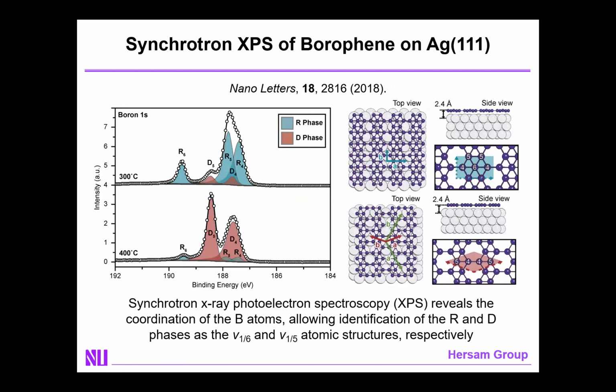And as a result, you need to use other methods, and one that was particularly useful was synchrotron X-ray photoelectron spectroscopy. And this allows you now to reveal some of the chemical bonding that's occurring in these 2D boron layers. And in particular, for the so-called R phase that I introduced in the last slide, what you can see in the boron 1s spectrum are three distinct peaks, which suggests that there's three distinct coordination numbers for boron in this structure. And if you take possible rectangular unit cell structures of 2D boron and consider which of those can have three different coordination numbers for boron, you learn that there's only one plausible possibility, and that is the so-called V1/6 structure here, wherein you have 1/6 of the boron atoms missing in the otherwise triangular lattice.